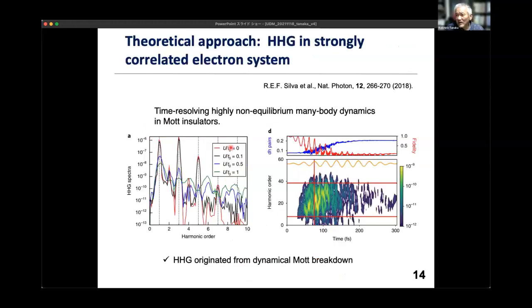And very recently, theoretical works have been carried out for high harmonic generation. The Silva group reported time-resolved, highly non-equilibrium many-body dynamics in a Mott insulator. This is a high harmonic generation theoretical calculation, and they showed breakdown is playing a very important role. Here you can see this is the excitation light, but the high harmonics occur in the very beginning of the pulse, like this, they predicted. And depending on the correlation, the spectrum changes a lot.